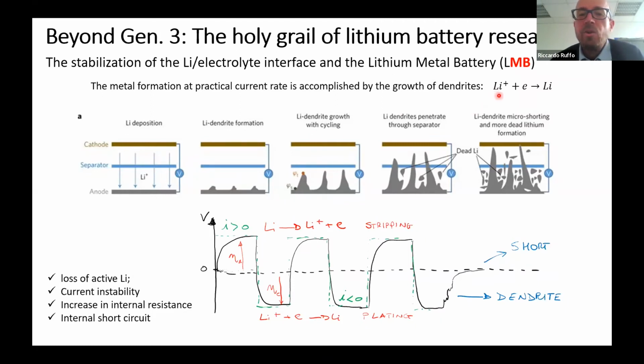When you try to plate a metallic foil like lithium, or other foils like copper and so on, with lithium plus to give lithium, what you have is that lithium doesn't grow, at least at the usual current rate, layer by layer, but grows with these dendrites. And these dendrites can be detached from the substrate, can penetrate the electrolyte, and can give short circuits, which is a dramatic situation in our cell.